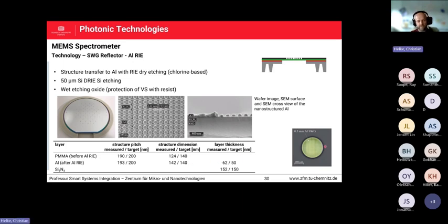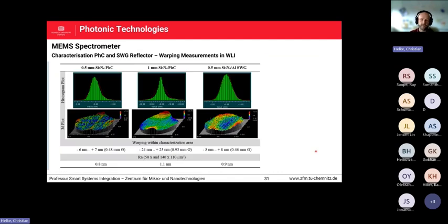At the end, what you can see here, for example, is a freestanding 0.5 millimeter aperture consisting of this thin silicon nitride membrane layer with all of these aluminum metal patches of 140 nanometer CD on it. And after the wafers were all fabricated, I performed some measurements because it is very important that all of these reflectors are flat and have very small warping and also very low roughness. And we measured this with a white light interferometer.